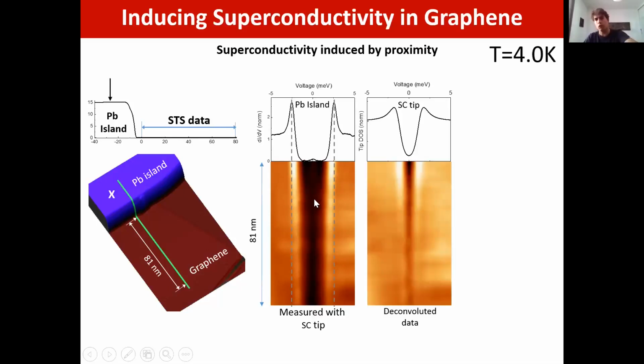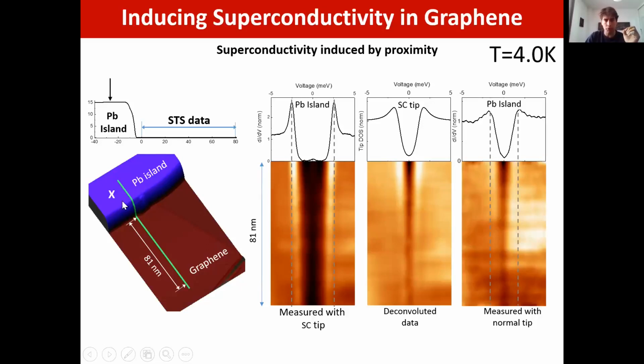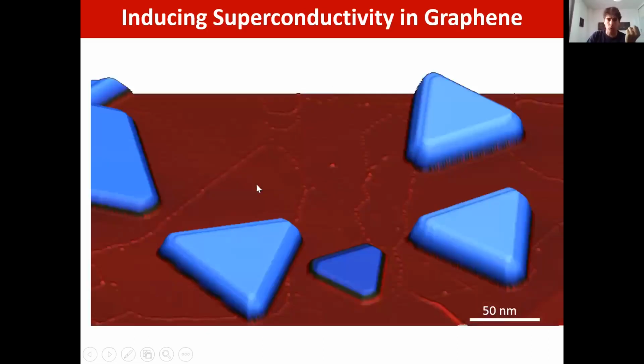Then if we want to recover the properties without the superconducting tip, we can do either a deconvolution, which we have here, or we can also, in this case, measure with a non-superconducting tip, and that's what we observe on exactly the same line with a superconducting and non-superconducting tip. And we can see that we have exactly what we expected from theory. So we can induce superconductivity on graphene. So all these regions here are superconducting graphene.